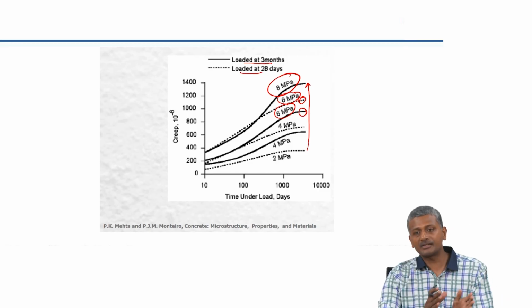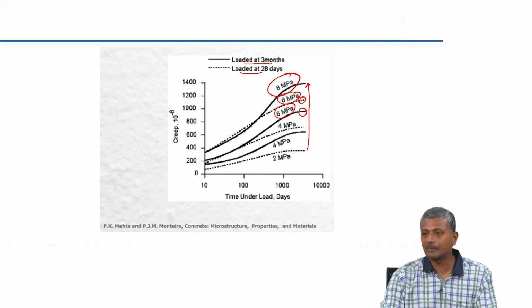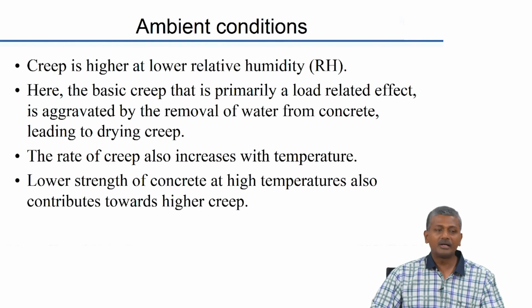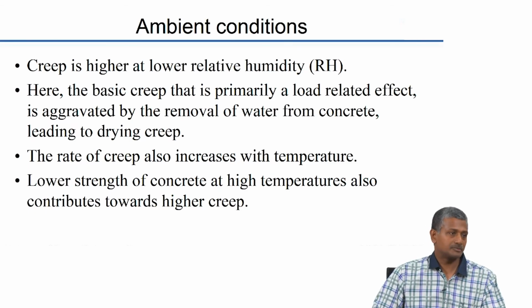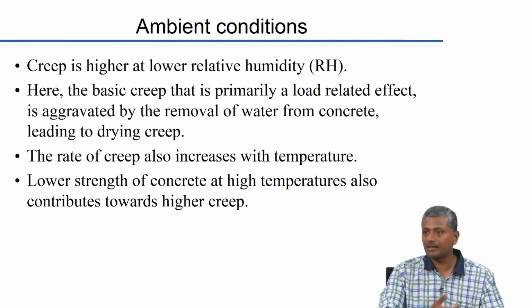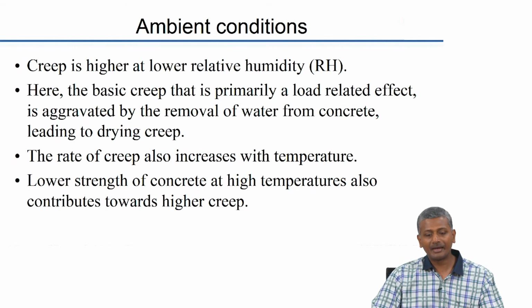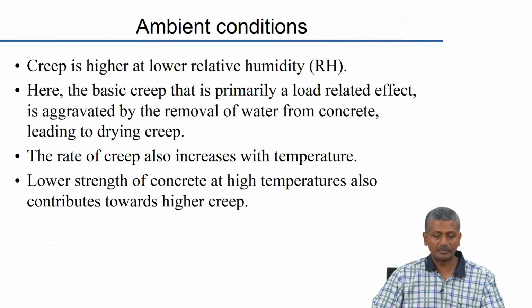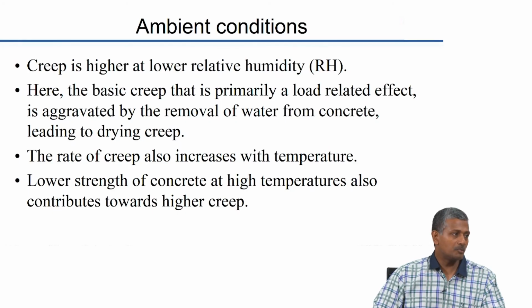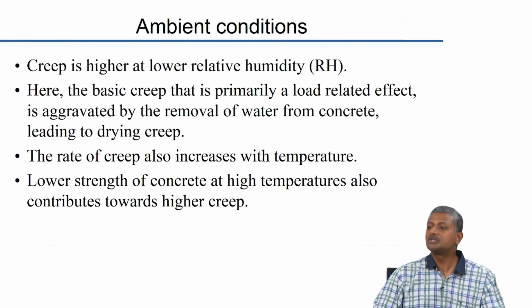So, applied stress to strength ratio and the age of loading both will determine the extent of creep that will happen in your system. The ambient conditions again have an influence obviously, because the more drying the conditions, the greater will be the effect of drying creep. Okay. If you have very low relative humidity and high temperatures, that will increase the rate of removal of water from the system, and your drying creep obviously is going to go up. Okay. Basic creep is primarily a load related effect and should not be subjected to any changes if there is change in the external environment.